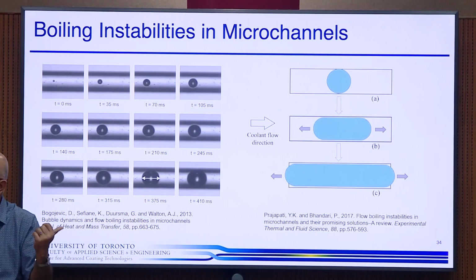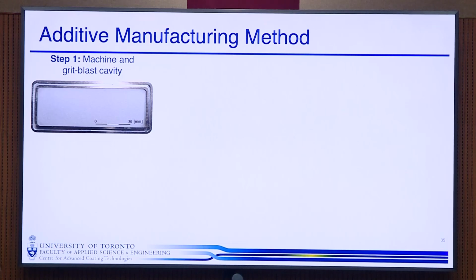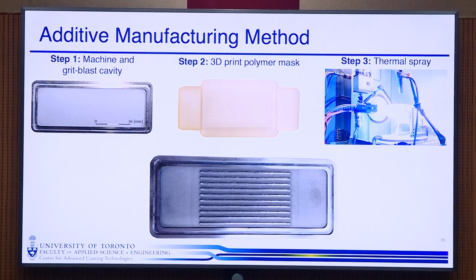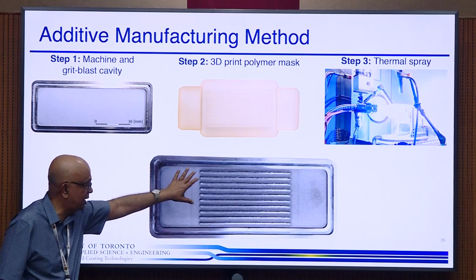And so this essentially blocks all your flow through your heat sink. And it can cause all sorts of trouble, but this is so unpredictable and so hard to control that until now, nobody is seriously using two-phase flow in things. Right? So what we wanted to do was, we actually decided to try this out. So we machined this. Again, we 3D printed our polymer mask, we sprayed, and this is what our parallel heat sink looks like.